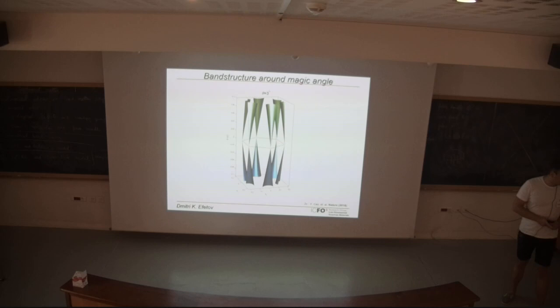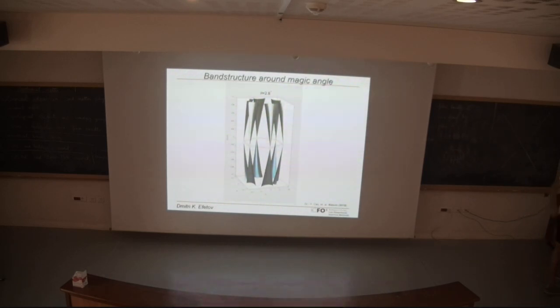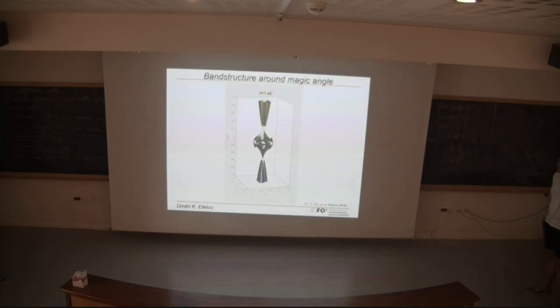Okay, and this is a video which I wanted to show, of how this band structure actually evolves. This was used in Pablo's paper, and they calculated the energy dispersion relation for different angles. So just take a look at this. Right, it works. Okay. So as you see, as the twist angle becomes smaller, the band structure flattens at the charge neutrality point. Then at around 1.1 degrees, it becomes super flat. And then if you reduce the twist angle more and more, the band structure becomes just weird, I guess, but not flat anymore.